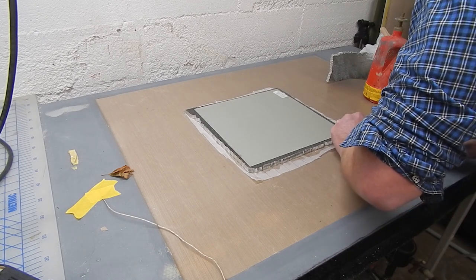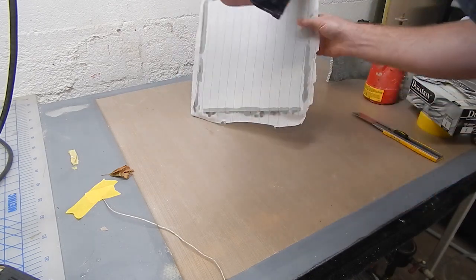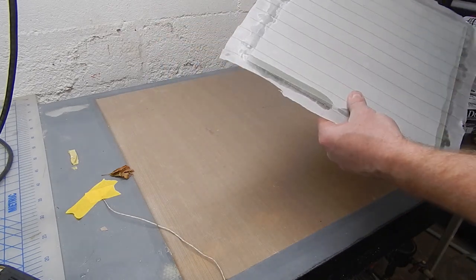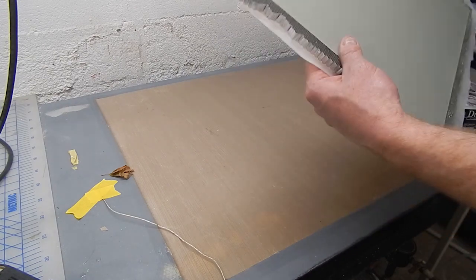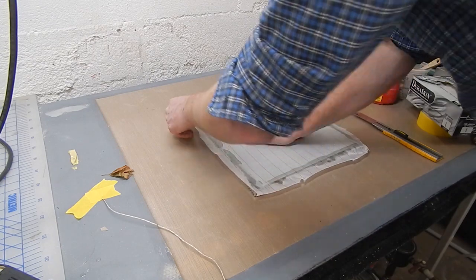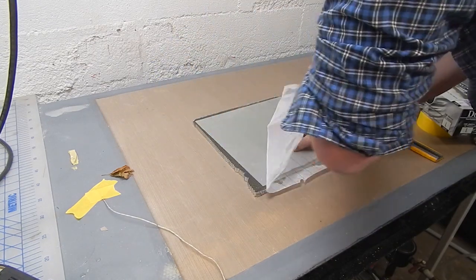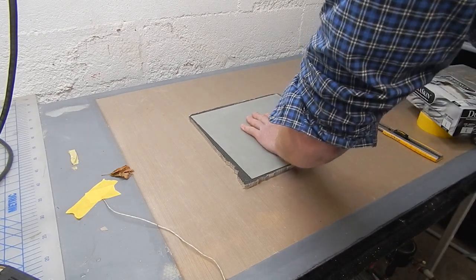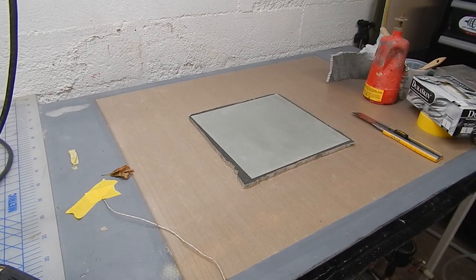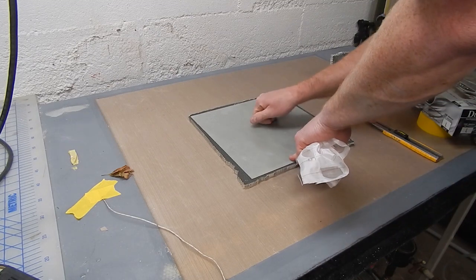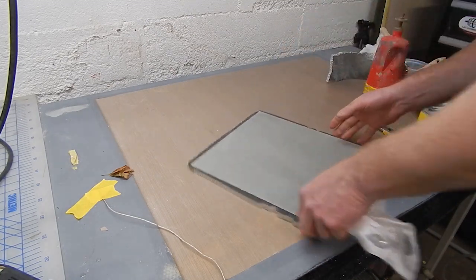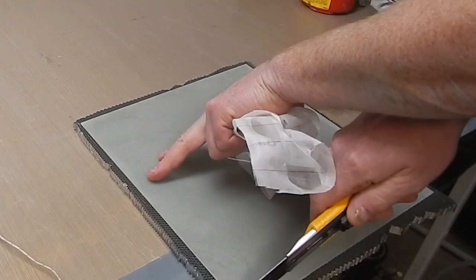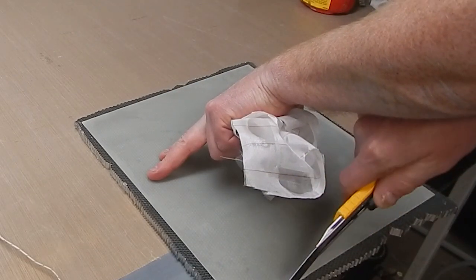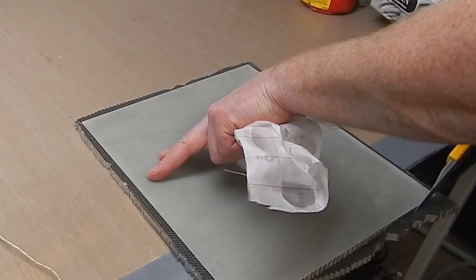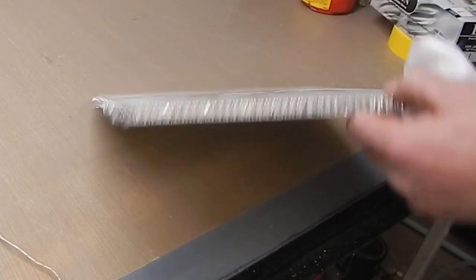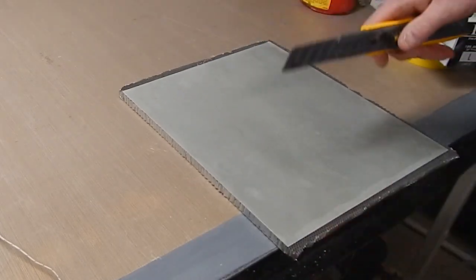Doing sketchy stuff with a razor knife, but it popped off really easily, and you can see where the resin crept around underneath, absorbed into the peel ply. But pulling that peel ply off should yield a nice flat surface with not too much extra resin to hold things up. And these came out pretty well aligned, and it certainly feels rugged and nice. You can see, looking at the top side, that there's less resin forming little fillets between the honeycomb cells where gravity did, in fact, pull it down. And I'm just using a razor knife to trim off the excess honeycomb from the perimeter.